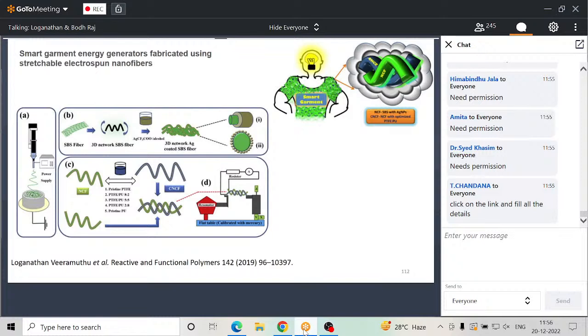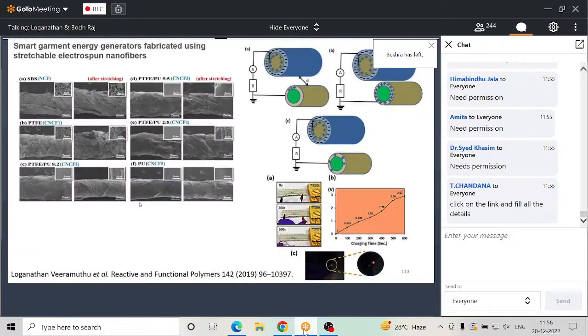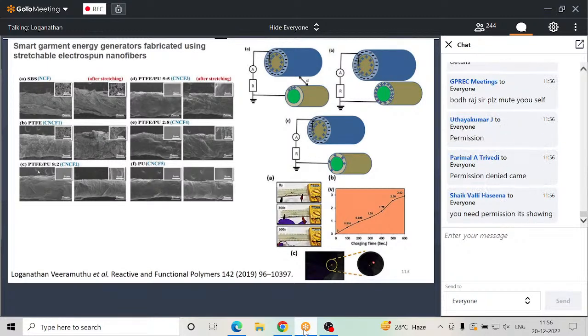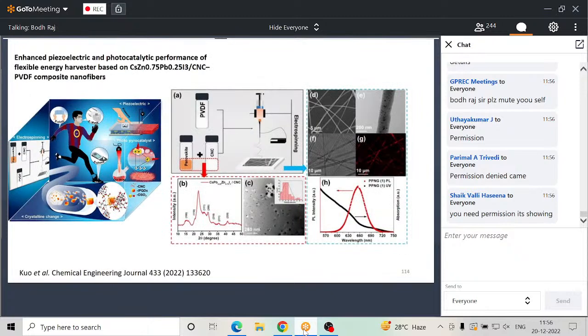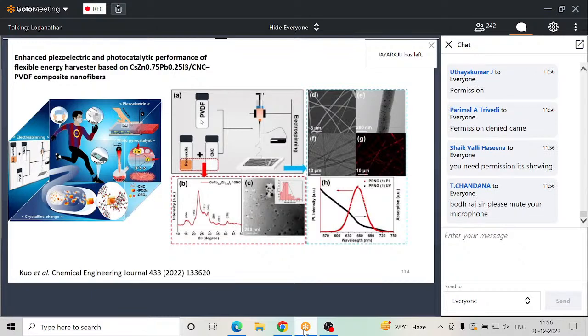And this is another article we recently published. In this, we are trying to use triboelectric systems. And we are trying to use some stretchable polymer like SBS. In this, we are trying to optimize the condition by using two different kinds of polymers, one is PTFE and PU. And finally, we do some PVDF based system, because we know that PVDF is a very good polymer. We mix the perovskites and CNC, and we form the fibers finally.